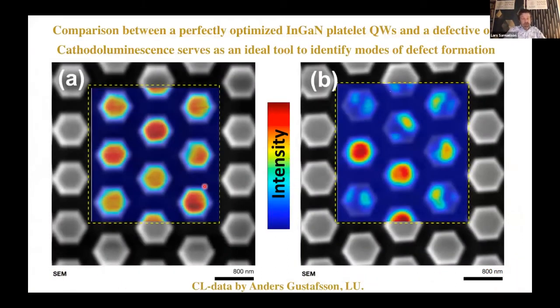So in the peak of where you had the green emitting one, you had this distribution of the emission. You see each of these platelets are perfect, defect-free. You can also see that if you make a small mistake, like a little bit too thick corner, then you can see by the cathodoluminescence imaging that you have just a few of these platelets working perfectly, in this case maybe 30% or so. So cathodoluminescence is an ideal tool to identify different modes of defect formation.